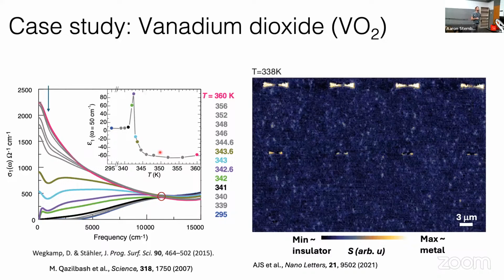And so one thought was maybe this is inhomogeneity. So the system maybe is at a local site, it is a pure metal or a pure insulator, but because there is an area averaged composition of insulator and metal, you're seeing intermediate values of the conductivity when you measure these spectra. So yes. Is this a film, and what's the substrate if it is a film? It is a film. And the substrate is sapphire. Okay. And that is very important because in bulk crystals, you do see a sharp first order like transition.